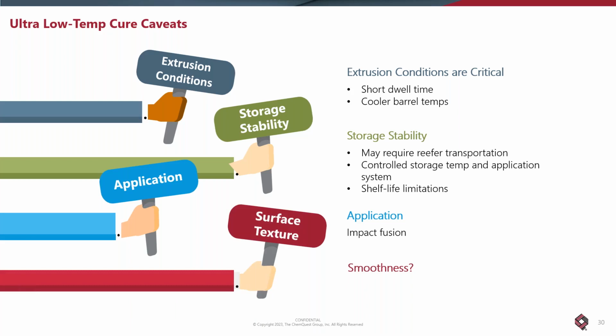The other thing with thermoset materials, we're fighting thermodynamics, we're fighting physics. Basically, we're trying not to have any cure until a magical temperature. And so it's like no cure, and then you want it all to happen at once. The real world probably doesn't work this way, so you may have problems with advancement or difficulty getting an adequate low melt viscosity during the cure process to give you the smoothness that you may be trying to achieve.